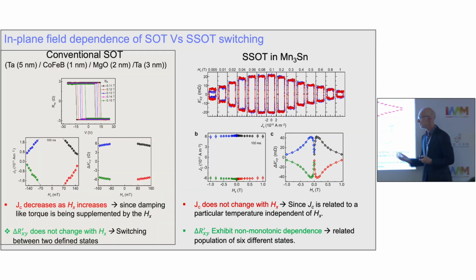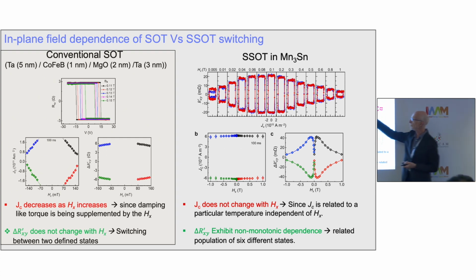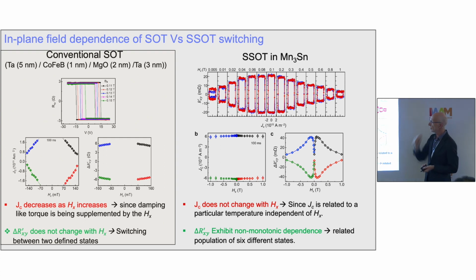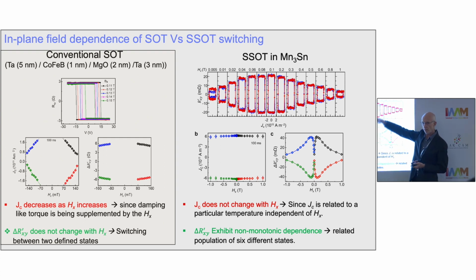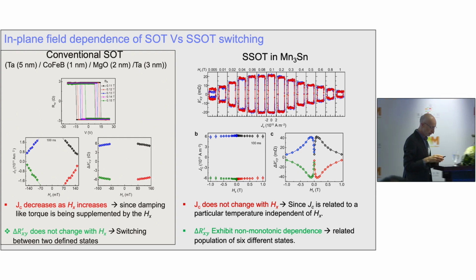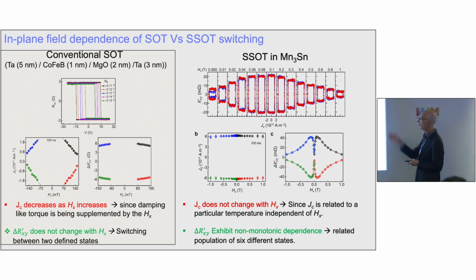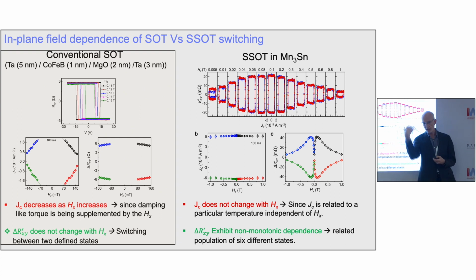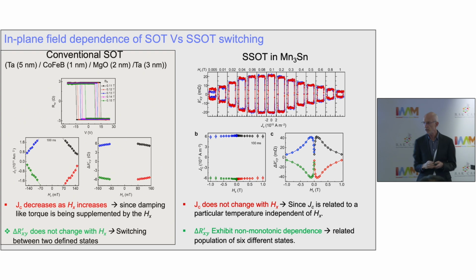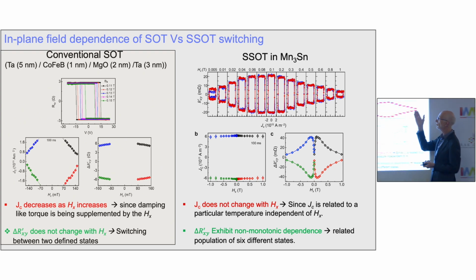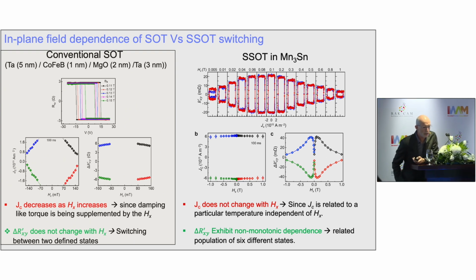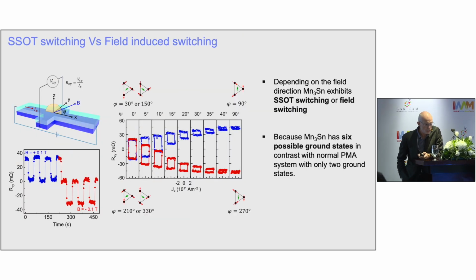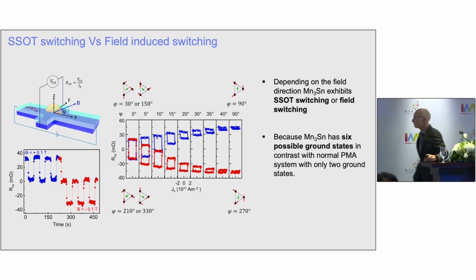Okay, so I just want to show you now, it's very interesting, by combining the magnitude of the in-plane field as shown here, we vary it from a few Gauss to 1 Tesla. We can change the magnitude of this anomalous Hall signal that we observe by switching with current. And in each case, the switching current is exactly the same, because it's the heating of the device that is needed. But in each case, we can control the degree of the antiferromagnetic chiral structure and the degree to which different ones of those 6 domains are configured. And then it shows you here, same thing.